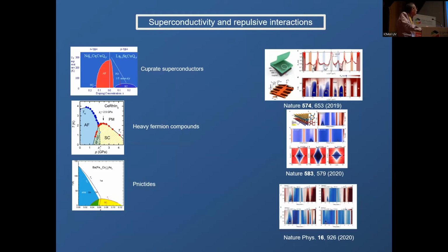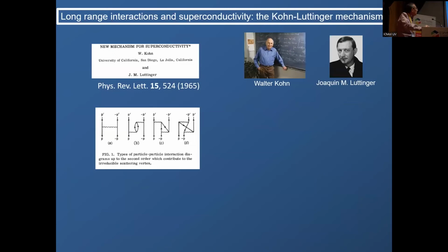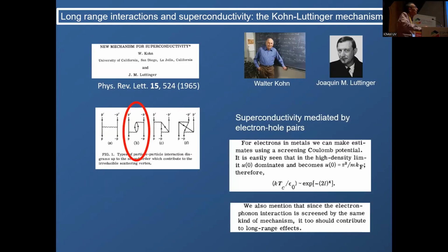As I said, in heavy fermions and so on, the Hubbard model is a good starting point. But there is a more general way of studying superconductivity. There was a seminal paper way back after the theory of superconductivity by Kohn and Luttinger, where they simply studied the electron gas. They noticed that when you put a charge in a regular metal, it creates a screening cloud with Friedel oscillations, and because of that, the screening potential sometimes becomes attractive. And they thought, well, maybe there is a kind of Cooper pair which can take advantage of these attractive regions, even when the potential created by a charge is repulsive towards another charge of the same sign. It's repulsive on average, but there are positions in real space where it isn't. And indeed, they found superconductivity in the electron gas only at incredibly low temperatures.